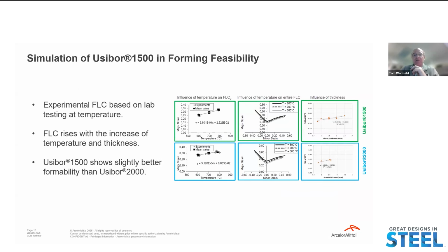Experimental forming limit curves have been developed at representative temperatures for the hot stamping process. Unlike cold stamping, a widely accepted formula doesn't exist for estimating the FLC, such as the Keeler equation, so the appropriate forming limit curves are a necessary component of the material card itself for simulation.